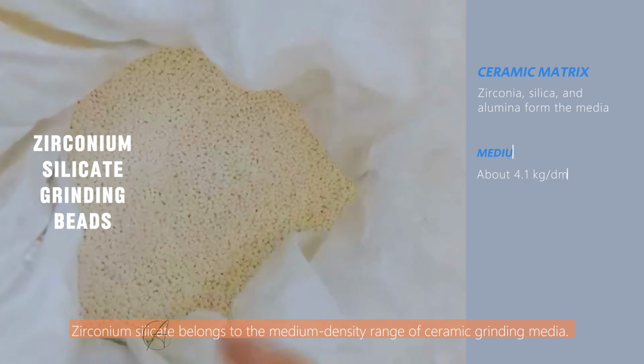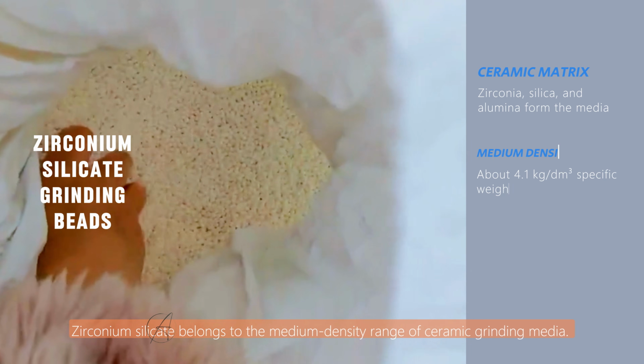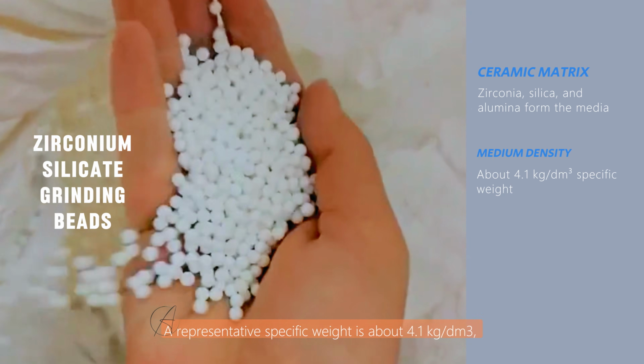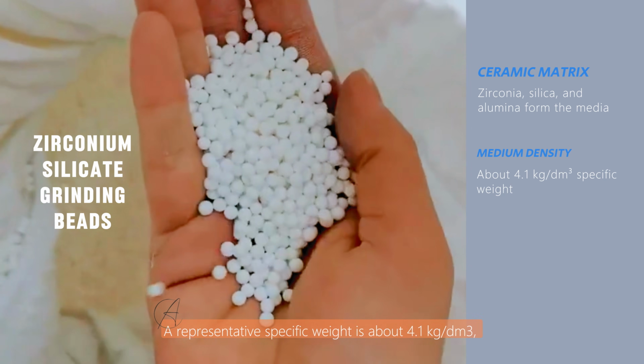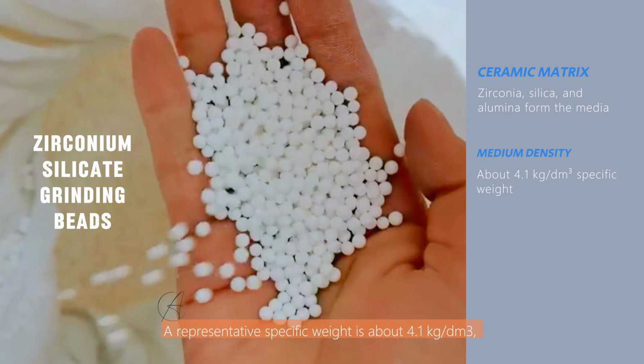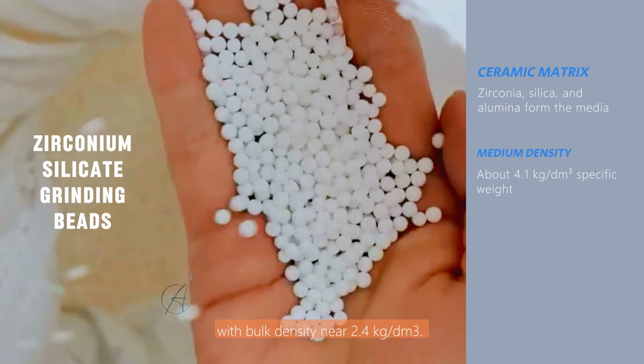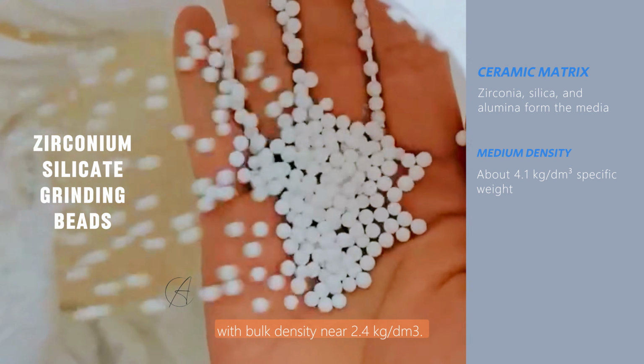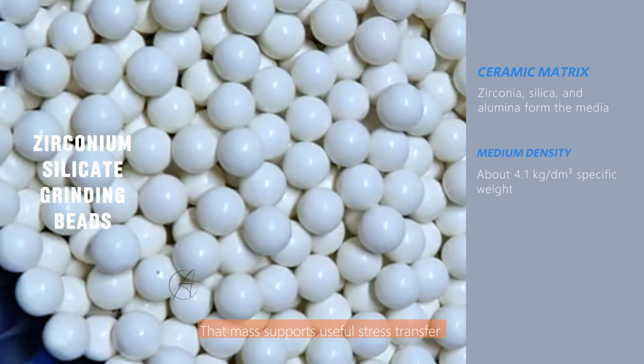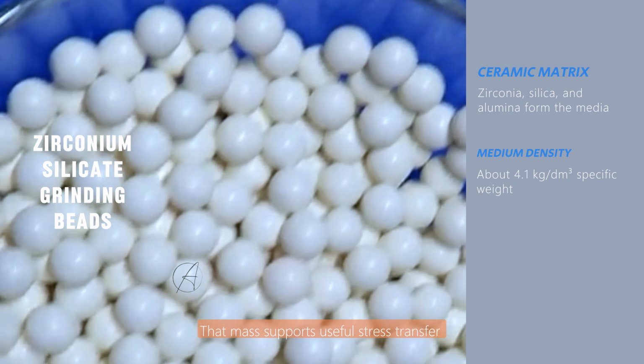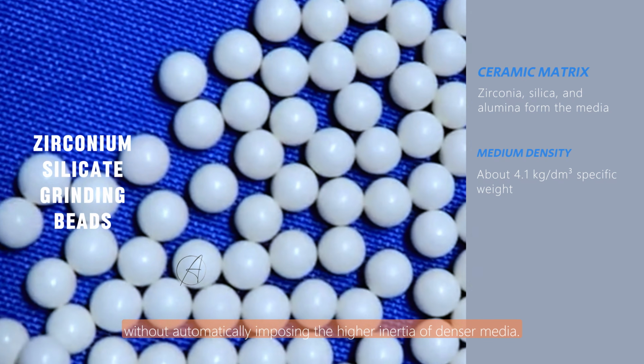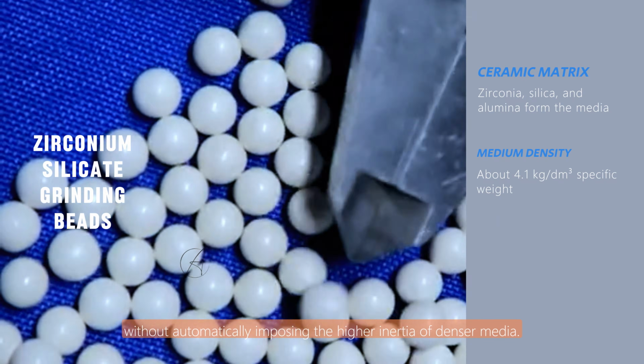Zirconium silicate belongs to the medium density range of ceramic grinding media. A representative specific weight is about 4.1 kilograms per cubic decimeter, with bulk density near 2.4 kilograms per cubic decimeter. That mass supports useful stress transfer without automatically imposing the higher inertia of denser media.